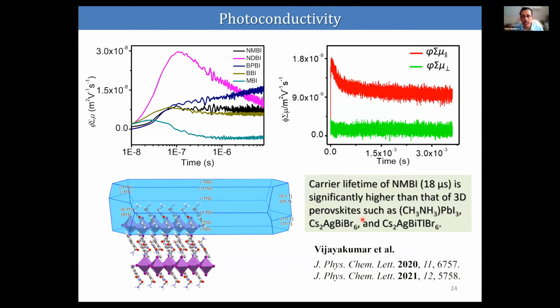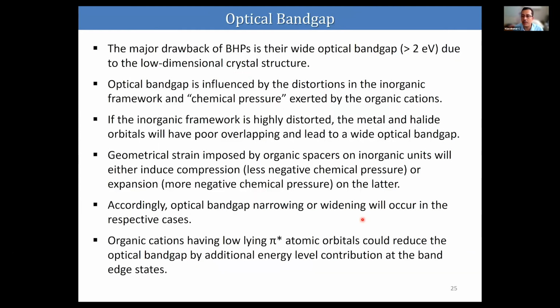And in the case of optical band gap, as I initially said, the major drawback of the bismuth halide perovskite is their wide optical band gap, which is about 2 electron volts, and it is mainly associated with the low dimensional crystal structure. And this optical band gap is basically influenced by the distortion of the inorganic framework. If the distortion is very high, the metal and halide orbitals will have poor overlapping, and that will lead to a huge optical band gap.